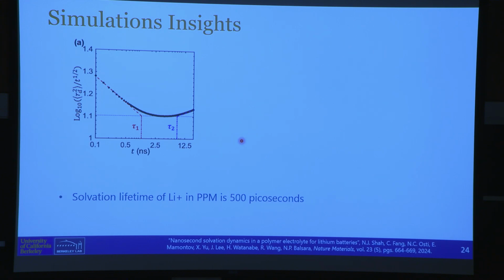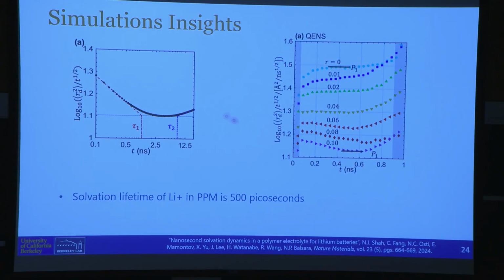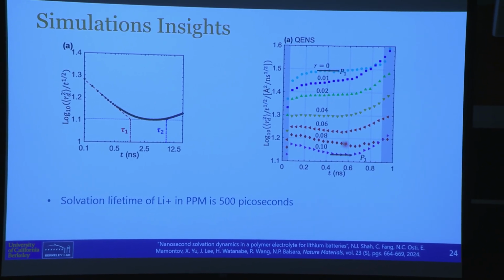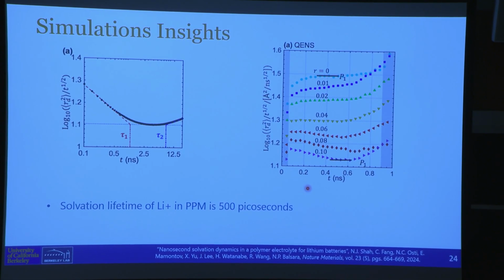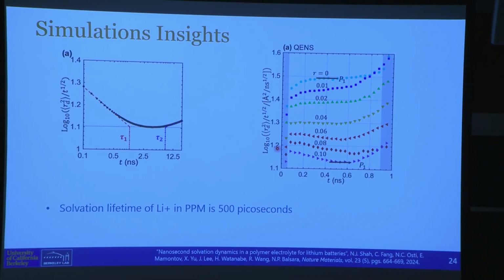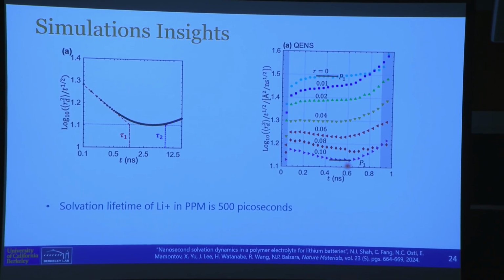And sure enough, when you do simulations, you get the qualitative structure that I talked about, mean square displacement normalized by t to the half that goes like I showed, and very much in the high concentration limit, there's nearly quantitative agreement, 1.2 versus 1.3, a plateau.